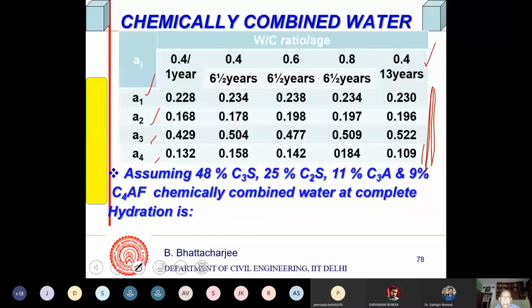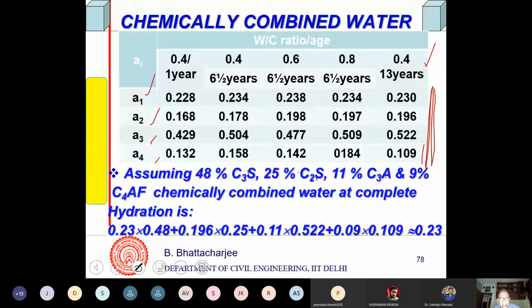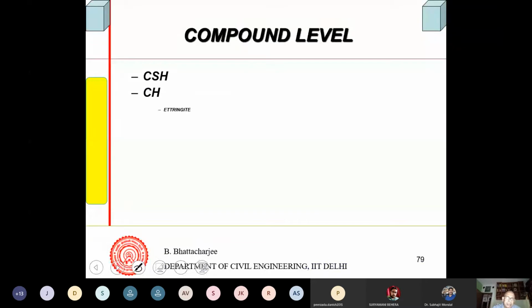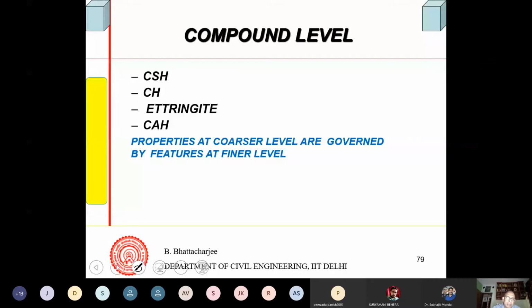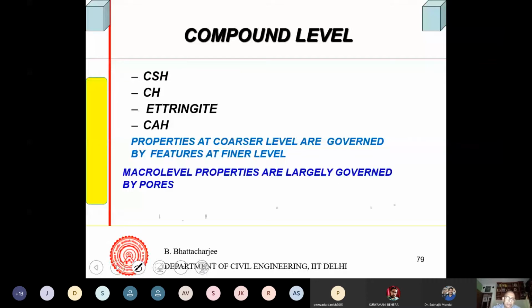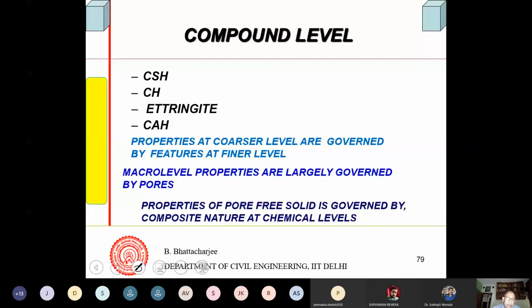So if you know the proportion of C2S, C3S, C3A, etc., you can find out the average amount of water you require for complete hydration of cement, 100 grams of cement, provided you are allowed to do so. Hydration is complete. So these products are formed, and we know it's around 23%. 100 grams of cement requires 23 grams.